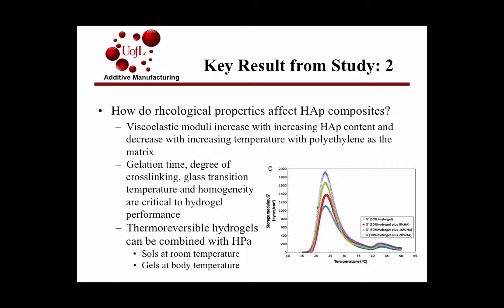They did determine that the rheological properties were important, so the gelation time, degree of cross-linking, glass transition temperature, and homogeneity were critical to this hydrogel performance. But they did mention that with these hydrogels, they were really ineffective without the HAP phase in terms of their mechanical properties. So they quoted that as a necessity for them to have any application at all.